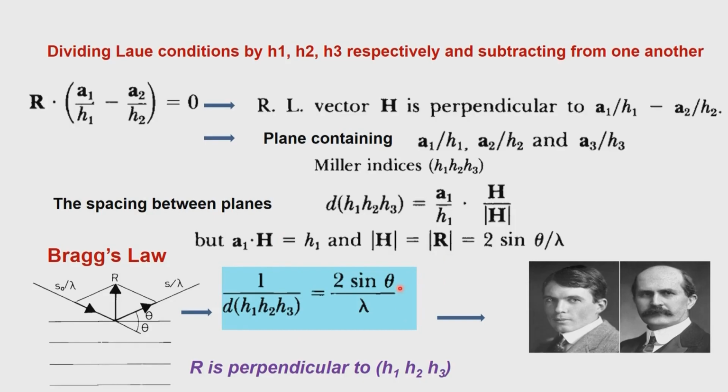Now, why do you ask that question? We ask that question because this just gives us only the geometry associated with the crystal. In fact, based on this equation we can calculate the cell dimensions, and therefore the crystal system, A, B, C, alpha, beta, gamma, can be determined by using this expression.